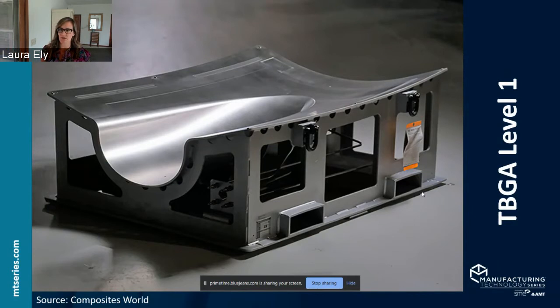You'd also be struggling, if you look at that depth, that aspect ratio for that tool, trying to figure out how to get that metal piece such that you could then machine and finish it. That would be pretty significant with traditional manufacturing. DED, of course, can move around, as Melanie mentioned, with the multi-axis. So I suspect that they turned this face sheet into a vertical orientation and were able to print it. DED, similar to powder bed fusion, has its own self-supporting angles, and then you have the possibility of adding some movement to the workpiece as well that gets you into additional geometries. So this is our first example of a level 1, which is indirect, but you can see the opportunities for both schedule as well as possibly cost implications for manufacturing tooling using DED.